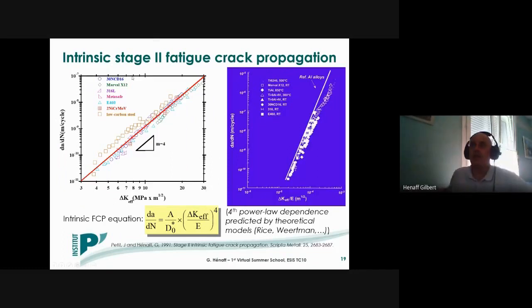When now we compare the intrinsic stage 2 fatigue crack propagation data obtained here in different grades of steels, you can see that we have almost a single relationship as soon as crack closure effects are taken into account. And this can be depicted by a fourth power law. And this is the same here when you compare different types of alloys.